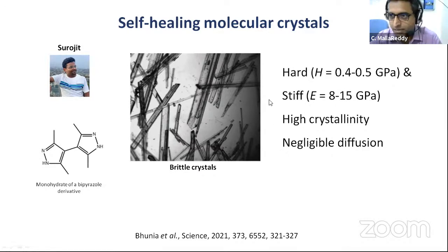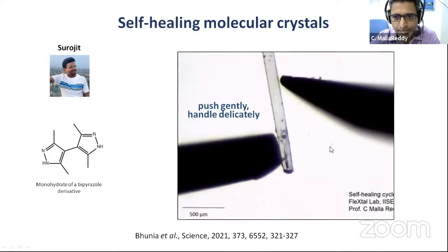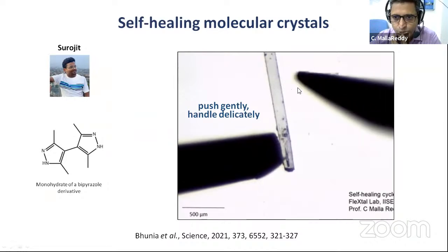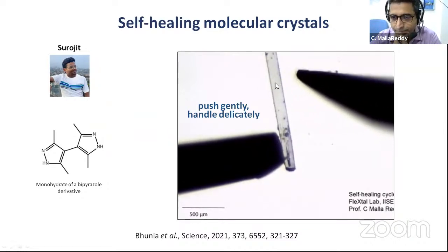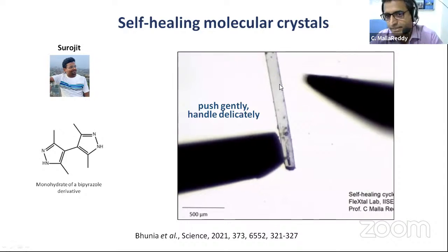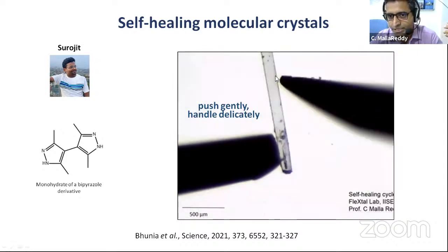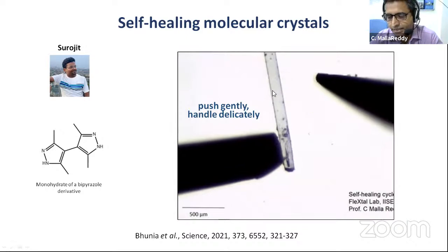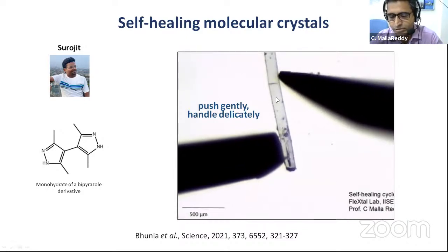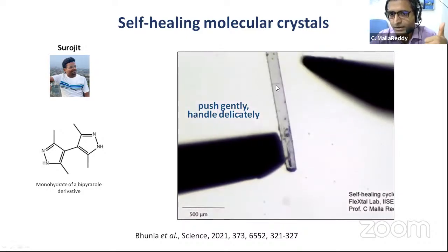And then these are perfect single crystals, and you can't expect diffusion in these crystals because they have a three-dimensionally hydrogen bonded network. So mostly you don't see any diffusion. When we were looking at the mechanical properties, my student found that when you push very gently and you have a big crack, these crystals pull together on their own, and then they rejoin, and the crack goes off on its own. Once it heals, the healing is actually perfect.